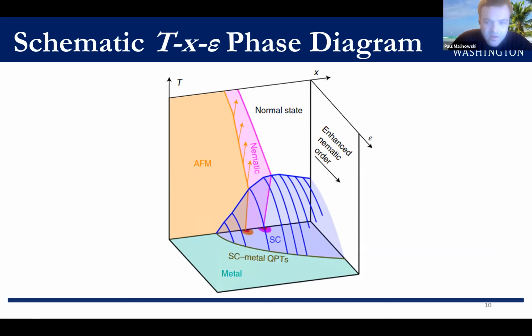responds. So this is what makes the huge sensitivity near optimal doping so intriguing, because as I mentioned, in that case, we are outside the magnetic phase. We expect to be increasing the strength of spin fluctuations, and yet we still see the superconducting state weaken considerably. So perhaps it really is the nematic fluctuations that are important for producing a high TC.